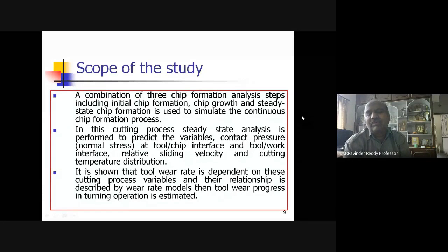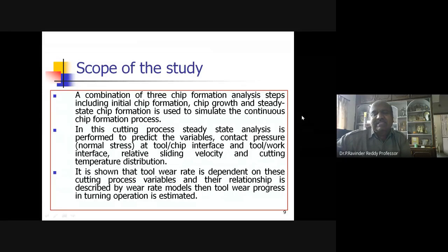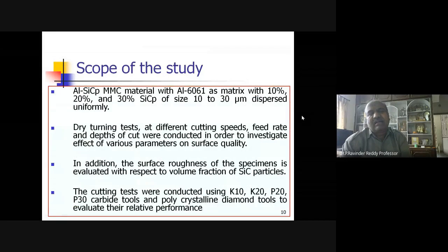It is shown that tool wear rate is dependent on these cutting process parameters and the relationship is described by wear rate models. Then the tool wear progress in the turning operation is determined. The aluminum silicon carbide particulate MMC material has aluminum 6061 as the matrix, with 10%, 20%, and 30% silicon carbide particulates of size 10 to 30 microns dispersed uniformly. So the influence of this silicon carbide particulate at 10, 20, and 30%.